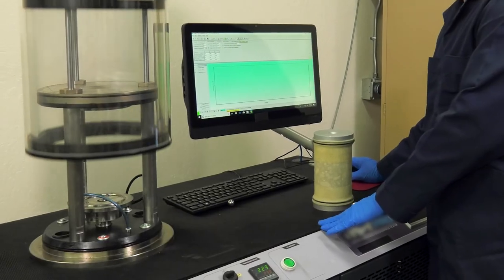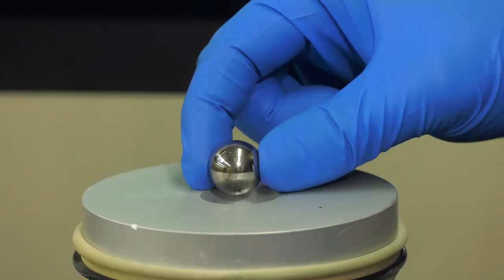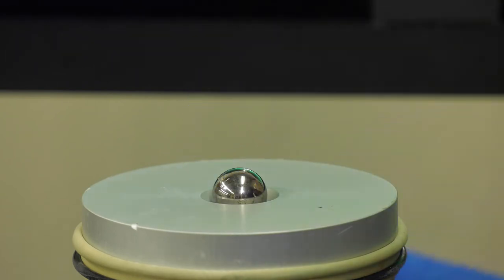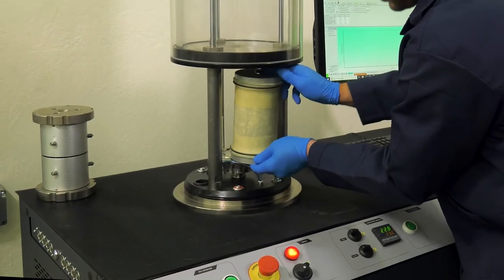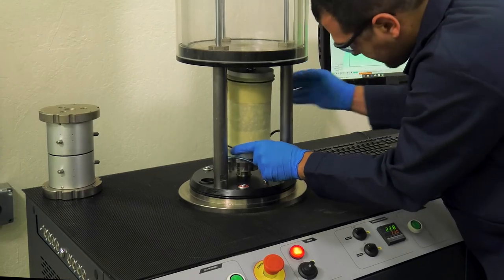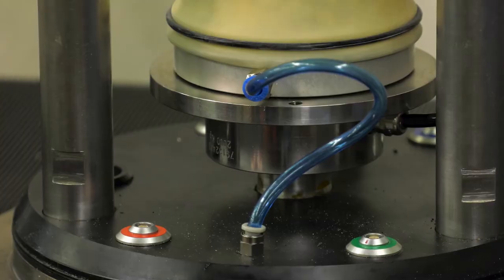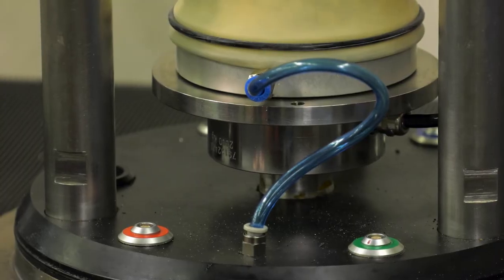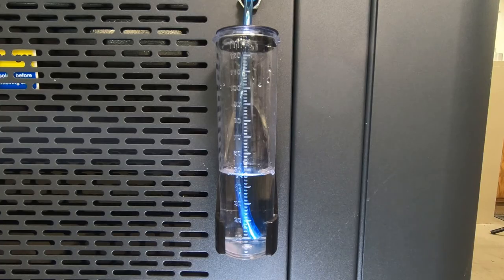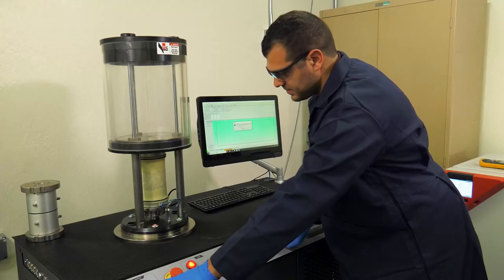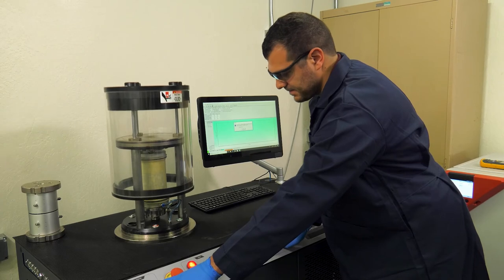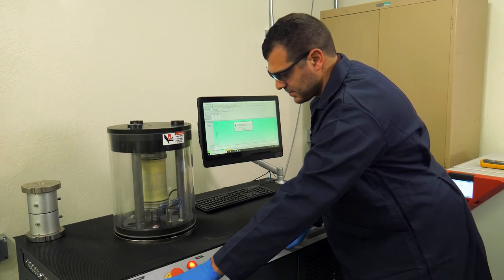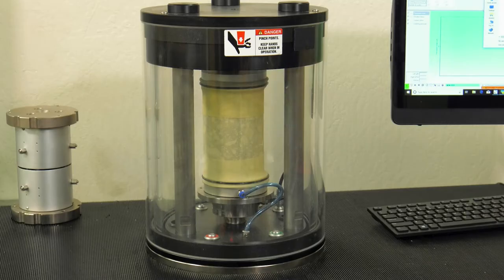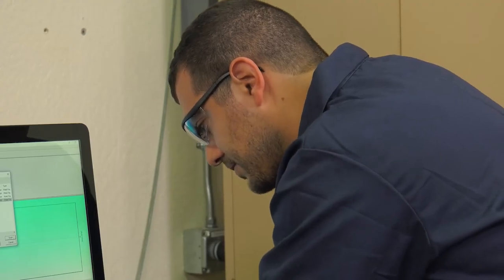Open the conditioning chamber. Place the steel ball on the top of the top platen and set the assembly in the chamber. Ensure that the assembly is secure on the stage. Then properly connect the drainage line to the loading platens so they are vented to atmospheric pressure through the bubble chamber. Close the AMPT conditioning chamber, and return the chamber to the target temperature. Pressurize the AMPT conditioning chamber. Pressurization should take approximately 10 seconds.